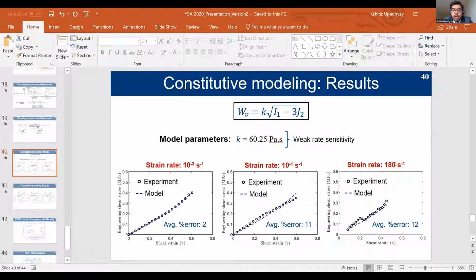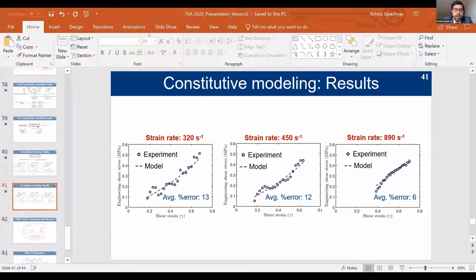If you see at 180 per second, even if there is variability in the stress strain response, I get around 12% error. If you look at the higher strain rate responses, 13% error, 12% error, 6% error. So although there is variability, which is very common in dynamic experiments, the model does a very good job in fitting the response if you look at the average percentage error. So this is what I minimize when I fit the model and not the modulus. Okay, thank you.